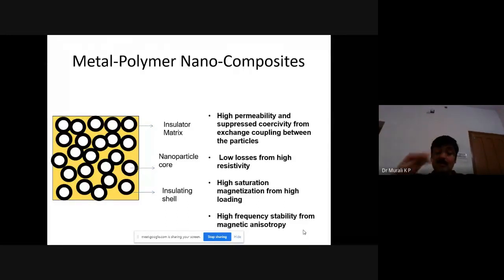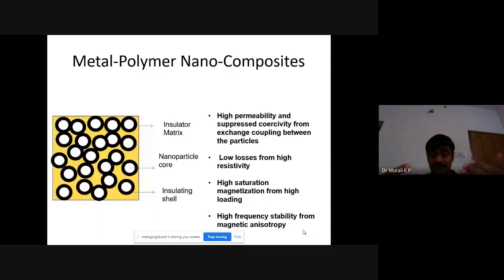So we will have high permeability and suppressed coercivity from exchange coupling between the particles. So we have to control the particle size, because it's a simple metal like cobalt or nickel or iron having a very thin oxide layer, so that when it is filled to a threshold level, if the particle size is so small, we can expect exchange coupling, which will enhance the permeability and reduce the loss. And since this core has an oxide coating and a polymer encapsulation, resistivity is very high, and it can reduce the loss.